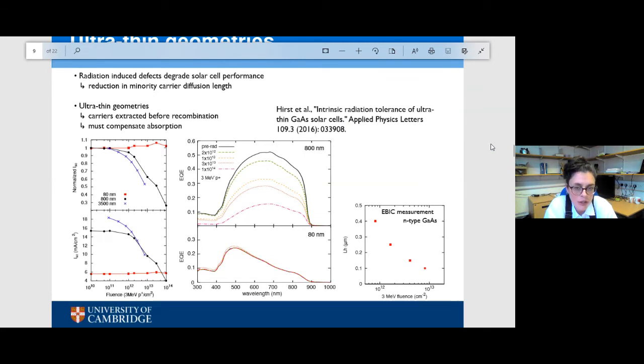Now, in ultra-thin geometries, we're actually relatively resistant to the presence of those defects because we can extract charge carriers before they recombine. And that's illustrated in the graph on the left here, where you see at the top your normalized short circuit current for 3 different device types, ranging from ultra thin at 80 nanometers through to much thicker devices at 3.5 microns. And you can see how their performance degrades as a function of proton fluence. However, the ultra thin device, we see a very flat profile, which is exactly what we want for space-based applications.